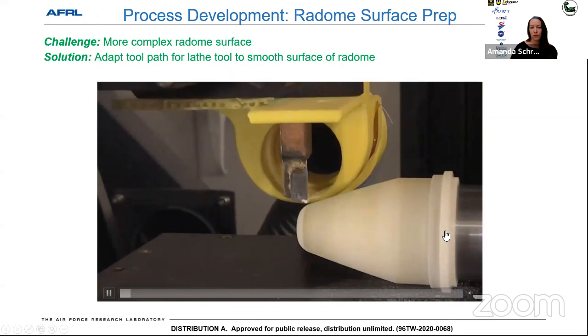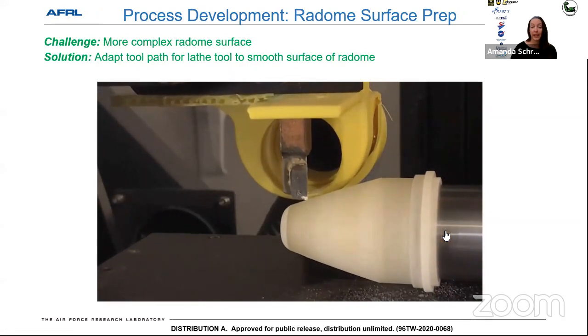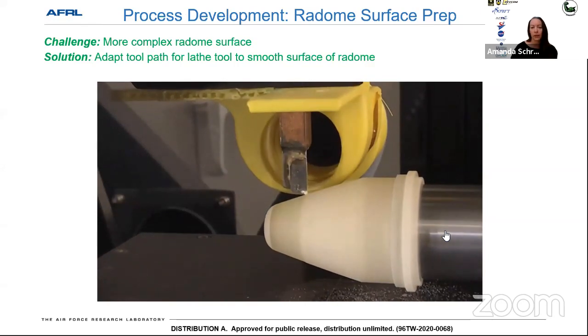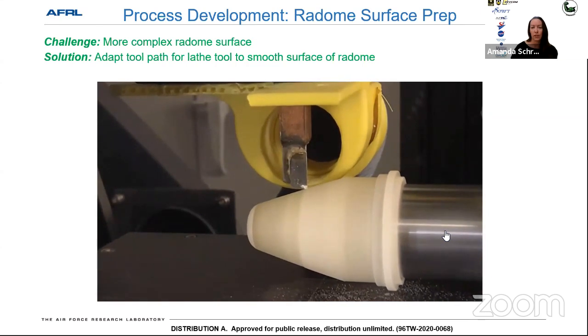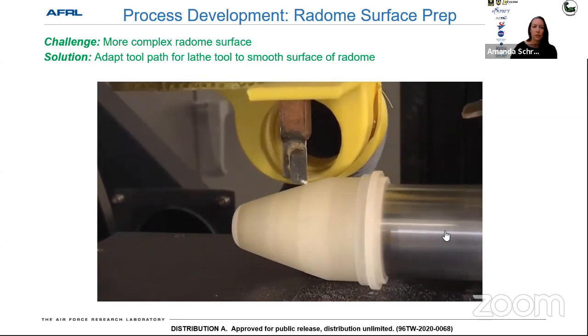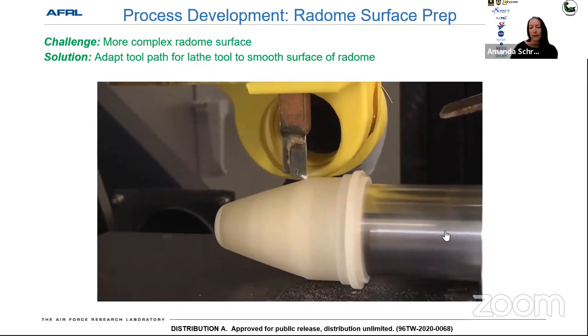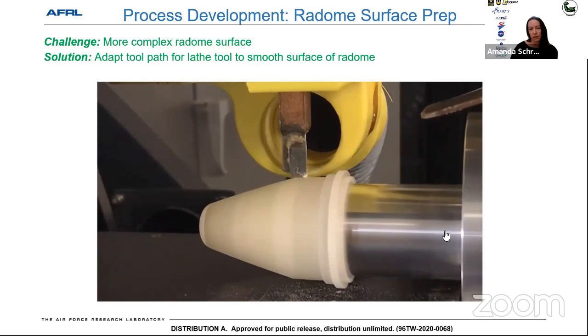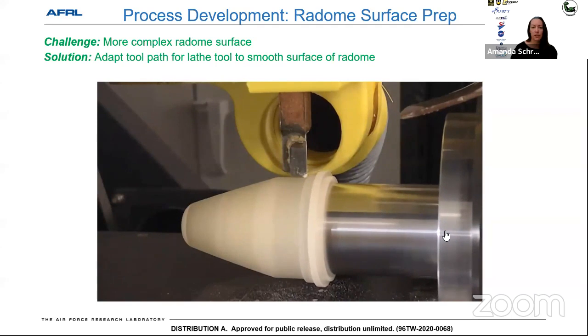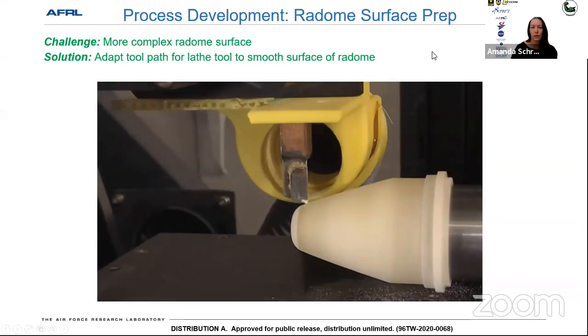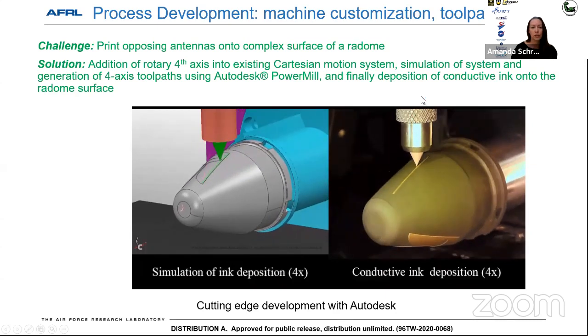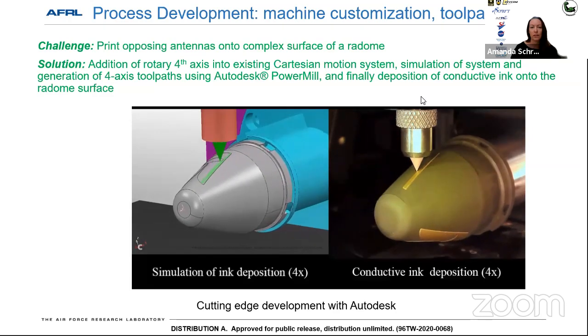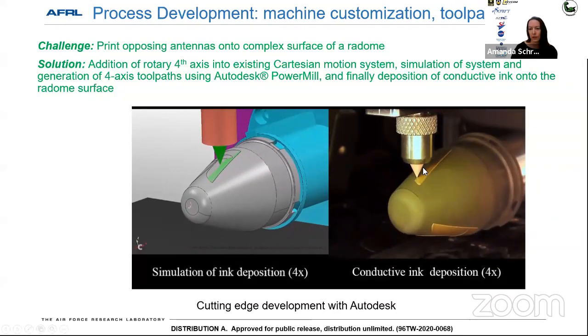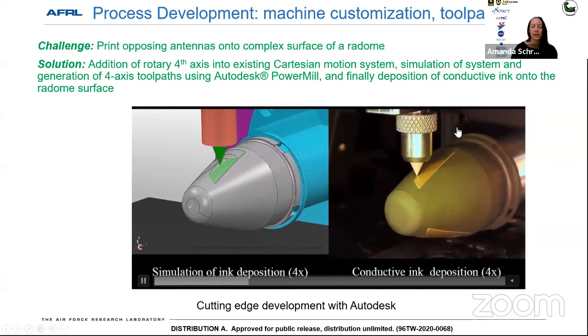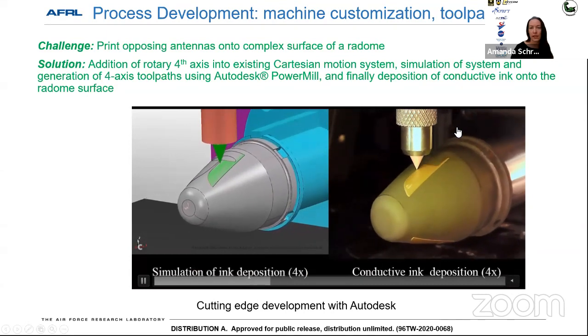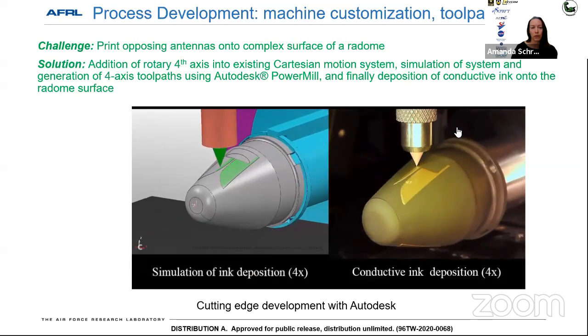Since that study, we've implemented quite a different variety of tools into our Nscrypt. At one point, we implemented a lathing tool with a vacuum. So what you see on this video is basically a way to smooth the complex surface of this radome before we print on it. There's many other things that need to be done before we use this very sensitive ceramic tip for microdispensing in the Nscrypt. So this was one step that we had, and then we started working with Autodesk to basically do the 3D simulation of the printing of that Vivaldi antenna. There's dual Vivaldis, you'll see one on each side. But one modification we made to the printer was to add a rotary stage. So basically that enables the software in the printer to rotate this radome to print on both sides of it.